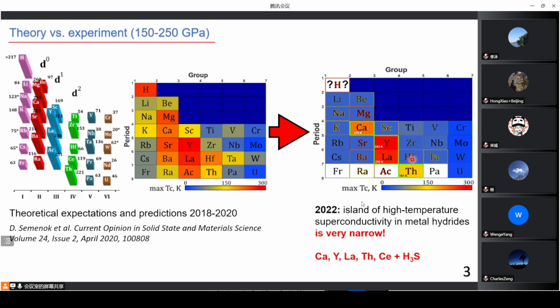So, as I showed, the group from the Chinese Academy of Sciences Institute of Physics investigated hafnium, zirconium. We investigated titanium, scandium, magnesium. It's not published yet, but I can say the preliminary results. As well, people investigated sodium hydrides, insulating, potassium hydrides, insulating, rubidium and cesium both form polyhydrides, but they're insulators and semiconductors. Strontium forms semiconductors, barium forms metallic superhydrides, but with very low TC, about 20 kelvins. So in fact, the island of superconductivity is very small and very narrow. That's the main conclusion at this point.